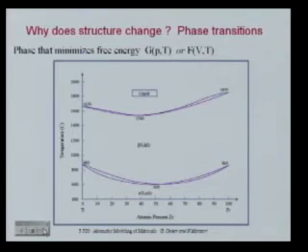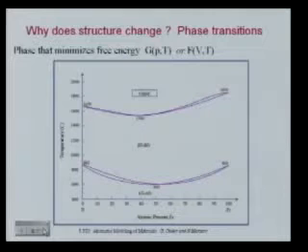Okay? But what about other excitations? There are some people who claim that this is really driven by electronic excitations. Okay? Because BCC phases also tend to have higher electronic entropy, and I'll show in a second why that is and how you could know that. If that's the case, then you shouldn't get this just doing ab initio MD. Then you should start explicitly including the electronic excitations, which can be done in ab initio methods, but routinely it's not done because it's a pain in the butt. Okay? And the problem is that as we do modeling, we often tend to make approximations, not because we can justify them, but because we don't know how to do them differently. We tend to make approximations of convenience sometimes rather than justify them.